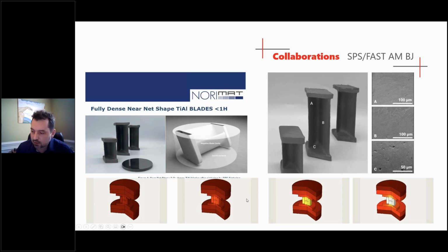So as you scale up, here's an example, some screenshots of the heating profile of a very small die. In this case, you'll see there's not really much to look at. The heating happens very uniformly, and there's not much to worry about. As the parts get larger, as the tooling gets larger, and as the geometries become more complex, this uniformity ceases to exist, and you need to plan for that. If you have a very asymmetrical tooling, you can end up with hot spots or cold spots, leading to non-uniform consolidation. And this modeling software allows us to predict that before investing in large, expensive tooling, enabling us to mitigate those issues and ensure proper densification.